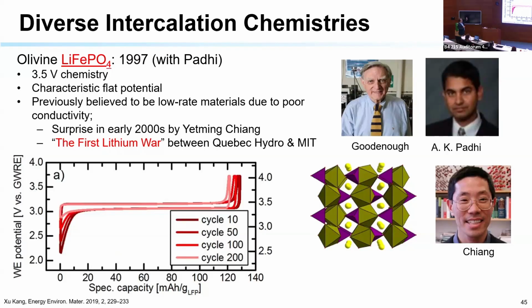And actually this material has taken over. Right now, most grid storage applications are based on this material. And just Tesla alone, about 65% of their cars, according to the latest numbers, are using this material. So this material is going to dominate the lithium-ion battery industry. It has lower energy density than some of the materials we use in portable devices, but for cars, for grid, it's just right. And people continue to improve its properties. We work on doping this with manganese. You can actually increase the energy density and do better.